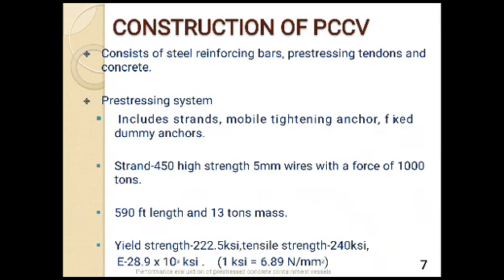This is the construction of PCCV. It consists of steel reinforcing bars, pre-stressing tendons, and concrete. Pre-stressing system includes strands, mobile tightening anchor, fixed dummy anchors. Strands are of 450 high-strength 5 mm wires with a force of 1000 tons and 590 feet length and 13 tons mass. Yield strength is about 222.5 ksi and tensile strength is about 240 ksi, and modulus of elasticity is about 28.9 × 10^3 ksi. 1 ksi is 6.89 Newton per mm square.